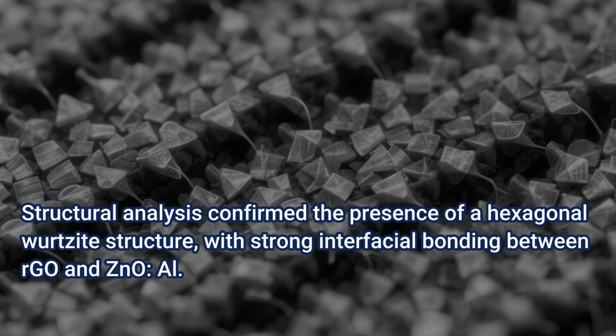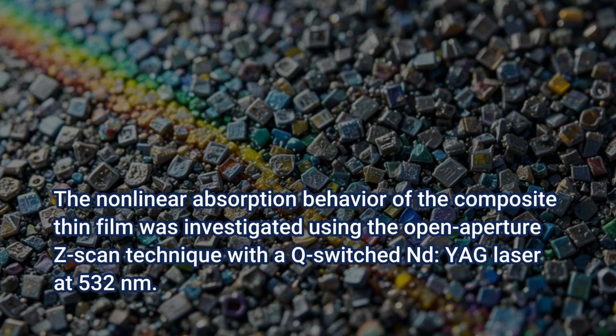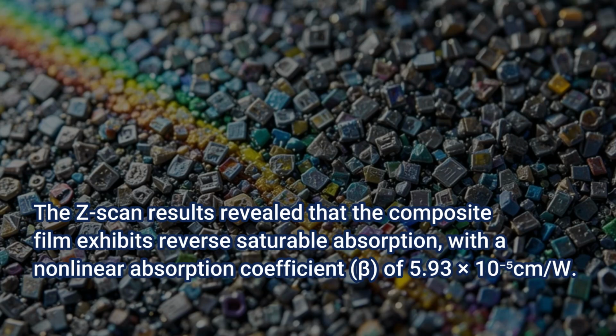Structural analysis confirmed the presence of a hexagonal wurtzite structure, with strong interfacial bonding between rGO and AZO. The nonlinear absorption behavior of the composite thin film was investigated using the open aperture Z-scan technique with a Q-switched Nd:YAG laser at 532 nanometers. The Z-scan results revealed that the composite film exhibits reverse saturable absorption with a nonlinear absorption coefficient, beta, of 5.93